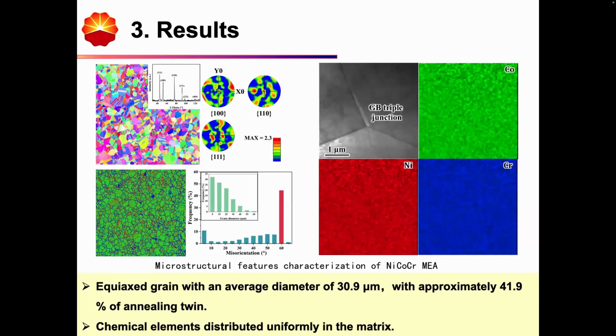We extracted some grain boundary triple junctions and examined the element distributions, and we can see the chemical elements are distributed uniformly in the matrix.